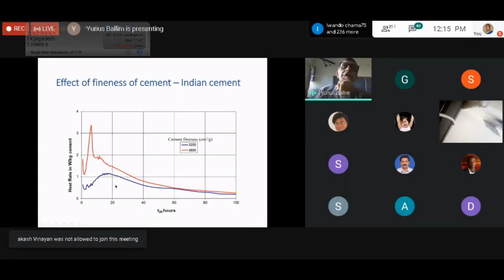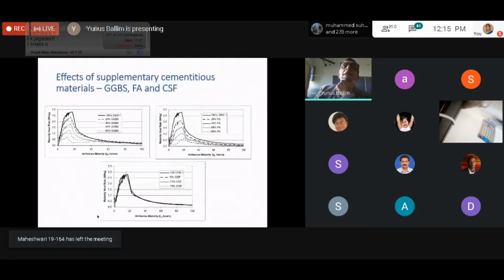I also want to show you the effects of these are the same cement from India, but one of them ground to what would be normal in South Africa, 3,200, I think normal in India as well. And then one ground to almost 4,000 square centimeters per gram, which is not as high as what you saw earlier. But look how significantly different the heat rates are. And I think, again, that this is an effect of the high calcium silicate in the clinker form in the Indian cements. And it would certainly be worth exploring what's going on here and what effect it has on heat development in large concrete structures.